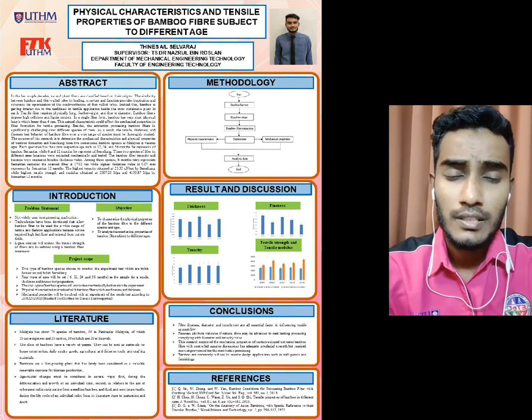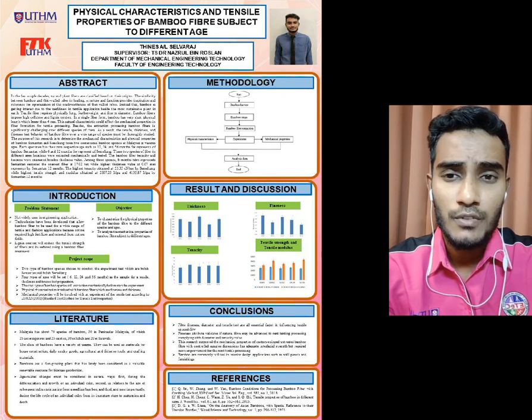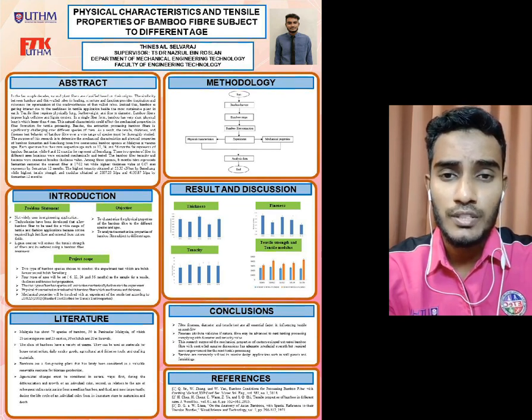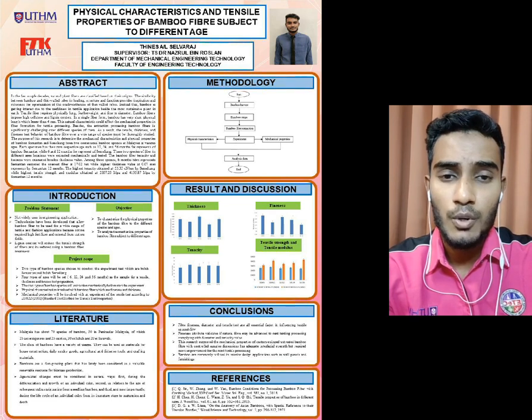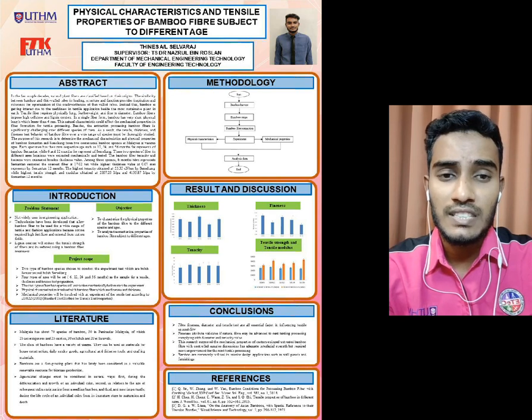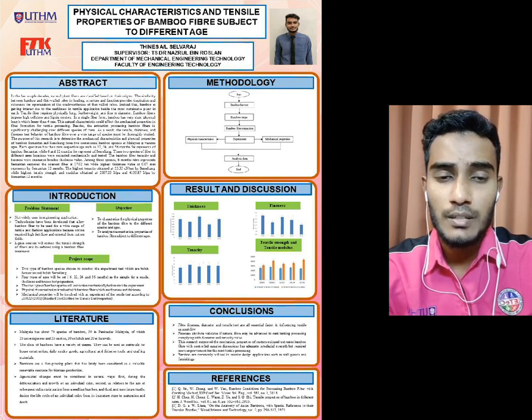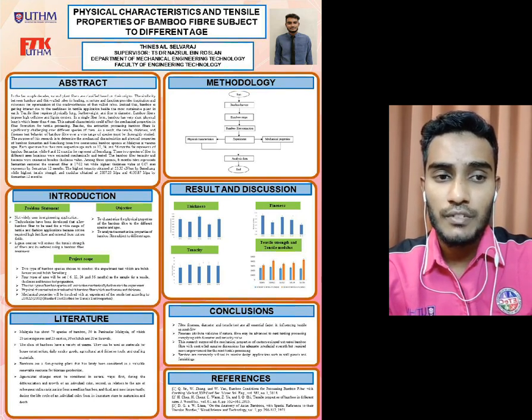Okay, based on the tensile modulus graph, the modulus value of Semalang bamboo fiber ranges from 3181.21 to 4135 MPa for different ages, while the Semantan bamboo shows change throughout the ages, ranging from 3462.54 to 5386.98 MPa. However, SAM 12 representing Semalang has the highest value of bamboo fiber strip at 2807.25 MPa, while SAT 36 representing Semantan has the highest value of bamboo fiber strip at 2605.8 MPa. This is because the length of the fiber is too long. There is some possibility for the fibers to be aligned away from each other. Thus, the interfacial bonding between the fiber and matrix will be disturbed, leading to a low tensile modulus.